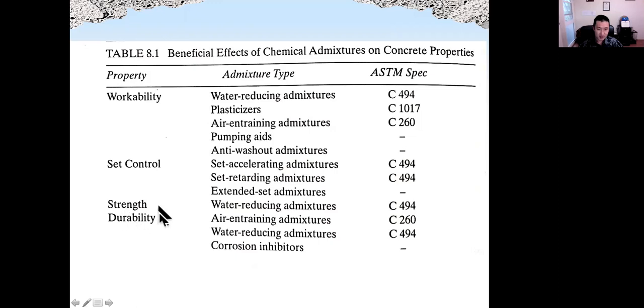Okay. For strength, we could have water reducing admixtures. Okay. If we use water reducing agent in concrete to reduce the water cement ratio, then the strength of concrete could increase quite a lot. Okay. For durability purposes, we could have air entraining agent for the concrete to resist freeze thaw damage, sulfate attack, alkali reaction. Okay. Water reducing agent and corrosion inhibitor sometimes can also be used for durability purposes.